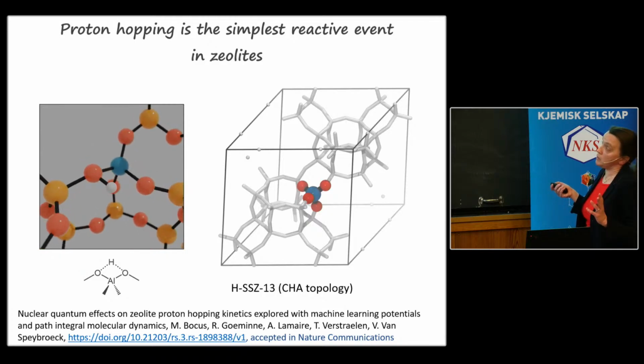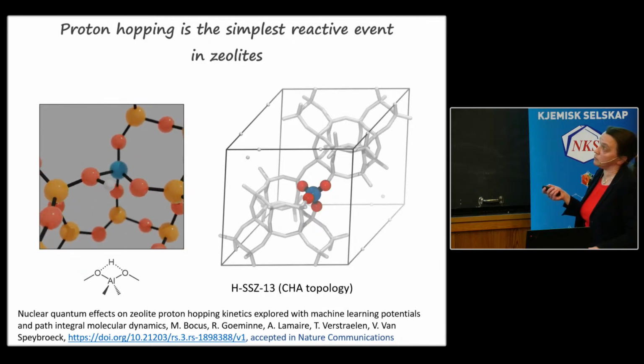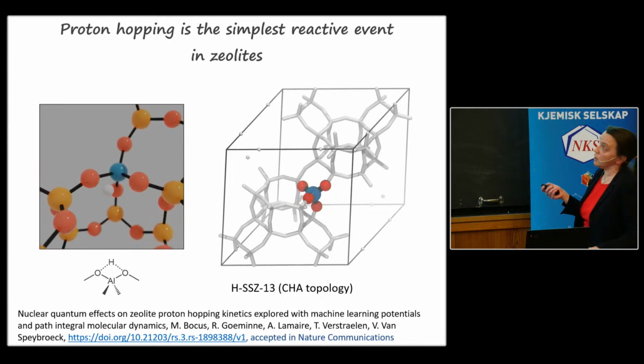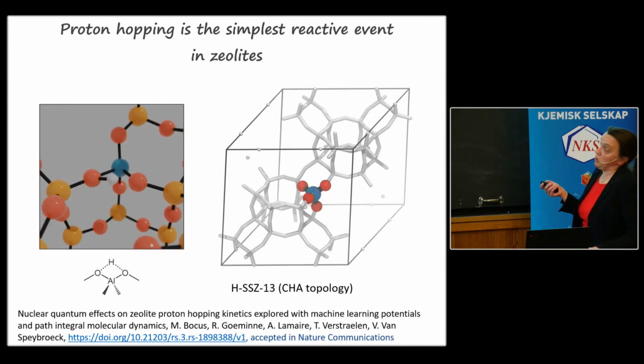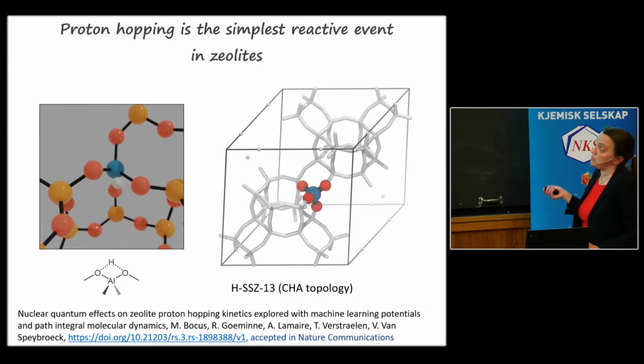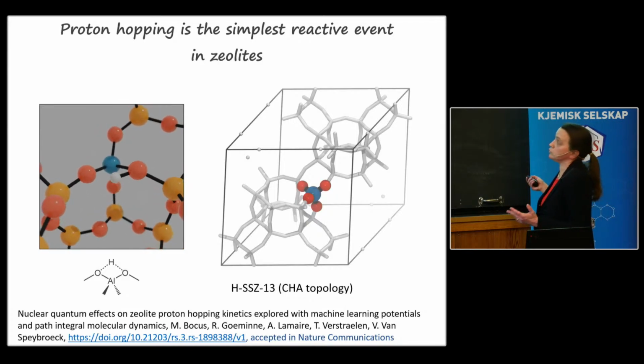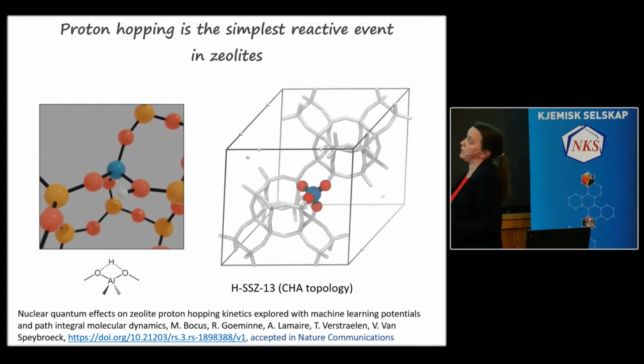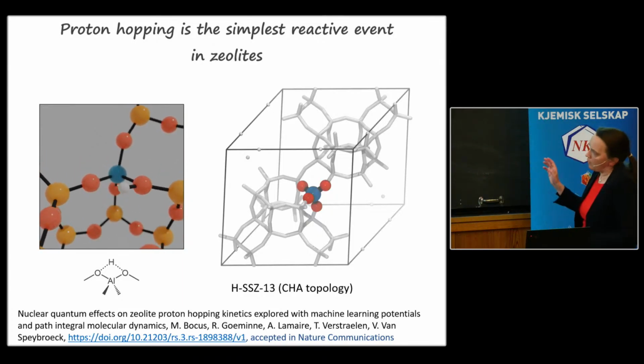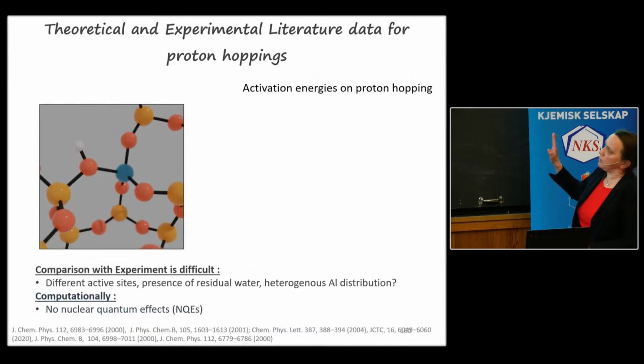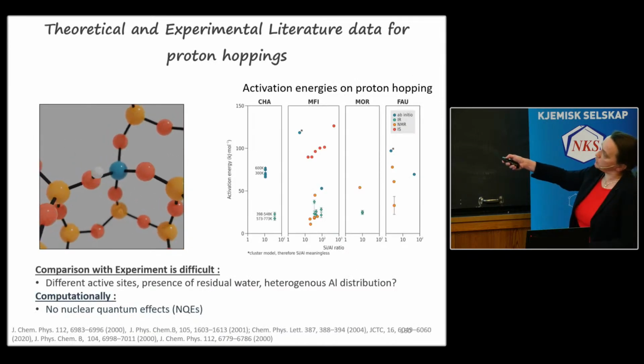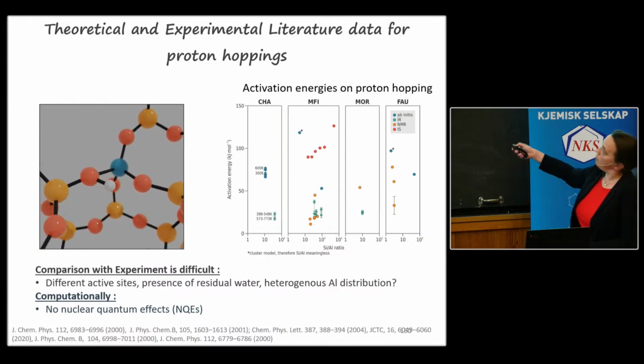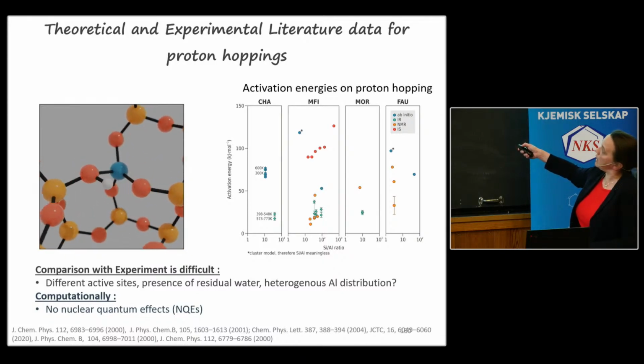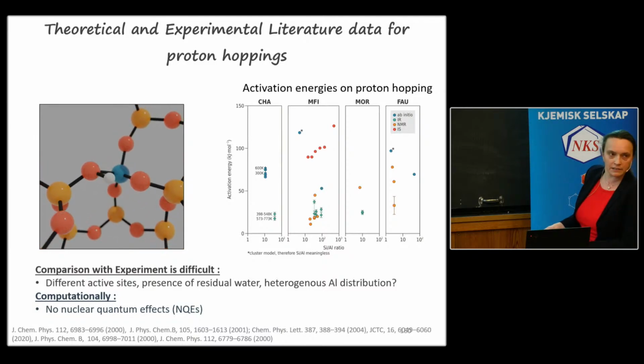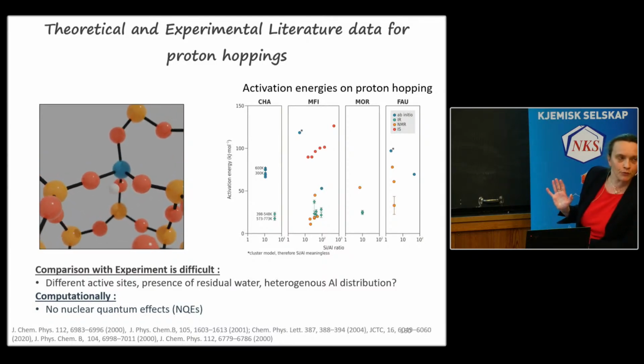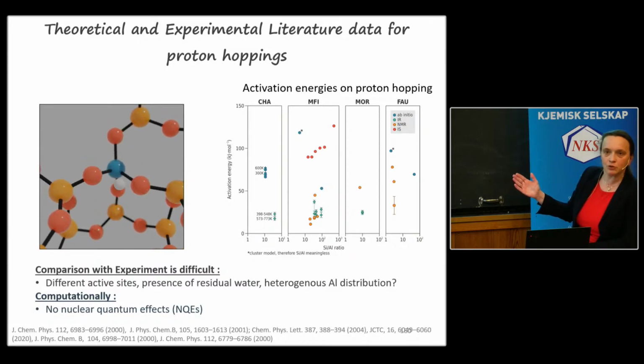You could say, okay, why do we want to study this? Basically, it's just a hopping of a proton from this side to another oxygen. And you could think everything's known, because it's a very basic process. But of course, we also wanted to investigate our methods, basically. And so it was good to start simple. Although, when you look at experimental results, and you look also at activation energies for this proton hopping, measured with different techniques, so infrared and NMR, we can see that there is quite some spread on the data. So also from an experimental point of view, it's not so straightforward, let's say, to know what happens.